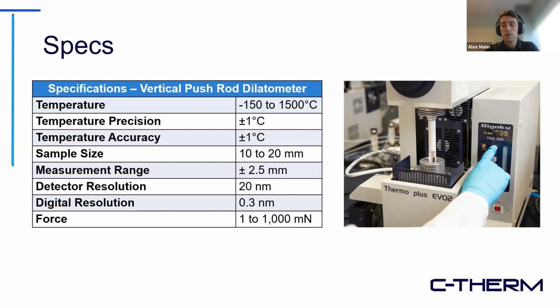Ideal sample size is 10 to 20 millimeters tall. The measurement range, the total expansion or shrinkage, is 2.5 millimeters, and the detector resolution is 20 nanometers. So it gets pretty precise, and the digital resolution, the number it will give you, is to the nearest 0.3 nanometers. The force that the rod exerts on the sample while resting can be changed from 1 to 1,000 millinewton.